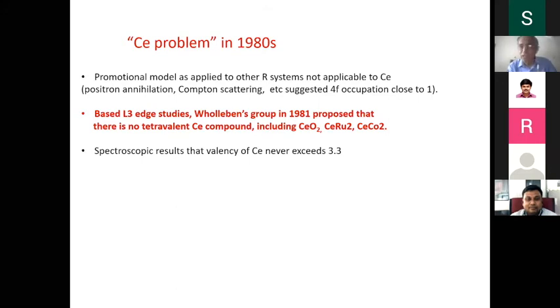But if you do spectroscopy by the techniques being employed to study the valence transition, that is photoemission spectroscopy and X-ray absorption spectroscopy, and people studied, okay, why not look at other insulating materials, and also other metallic materials which are considered to be not magnetic. CeRu2, it was believed there is no 4f electron. Cerium oxide, believed there is no 4f electron. But even in these materials, people found that they behave like mixed valence, like intermediate valence systems.